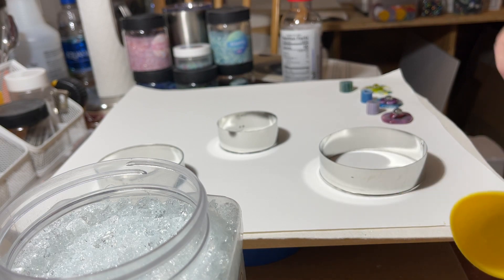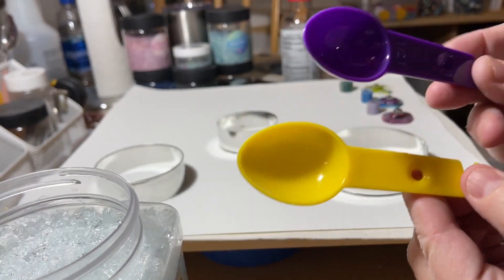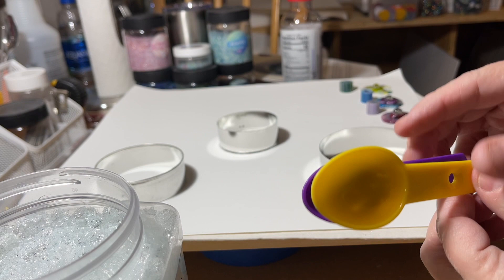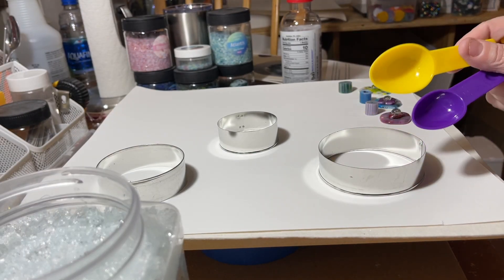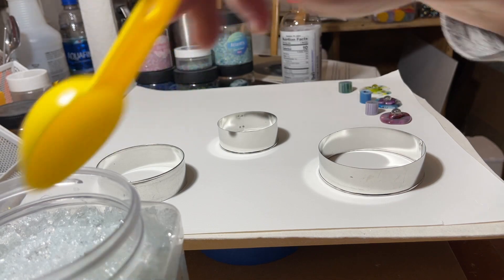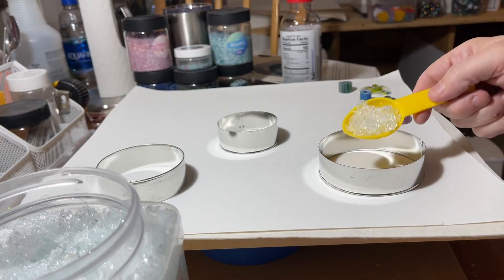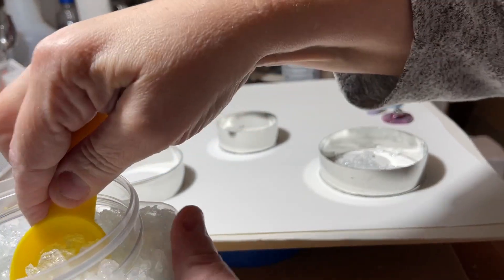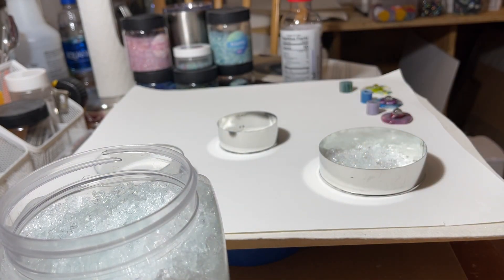I did find some measuring spoons that I'm not using in the kitchen that are great for down here. I have a one tablespoon and a half tablespoon one, so it'll be really easy to use twice as much clear as colors for this. For my first one, my largest one, I already took a look to see about what fills the bottom as far as clear, and it looked like about two of the tablespoons. I'm not being too precise — this is very chunky, coarse, clear. This was done quenched, where we put clear scrap into a colander, heated it up to about 1200, then plunged it into water and broke it up. So I'm just using a couple scoops.